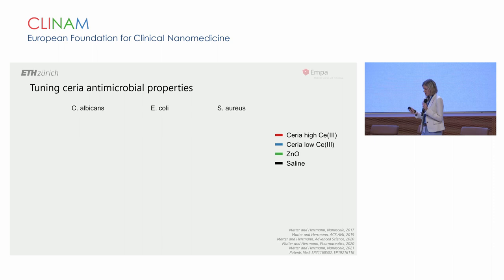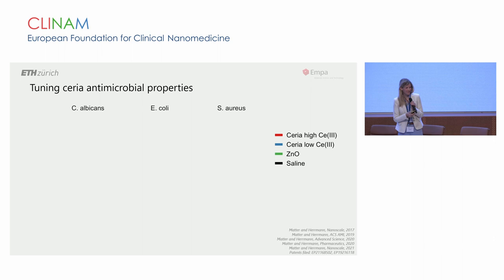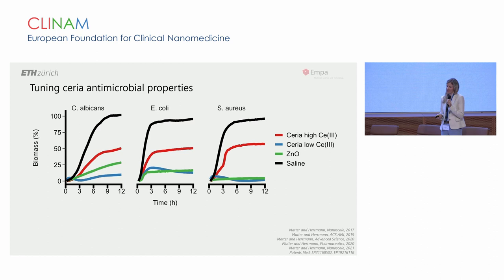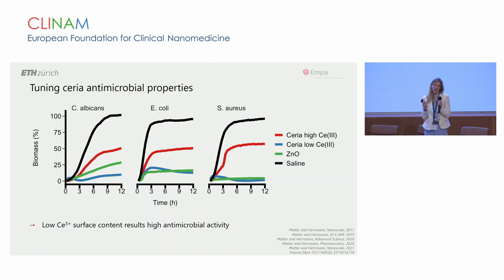We also confirmed that these particles can act as antimicrobials. In a simple planktonic assay, we look at the biomass as a function of time and compared different cerium particles to zinc. We can see that if we have a low cerium-3 concentration on the particle surface, we actually get a very comparable activity to zinc oxide at a comparable concentration.